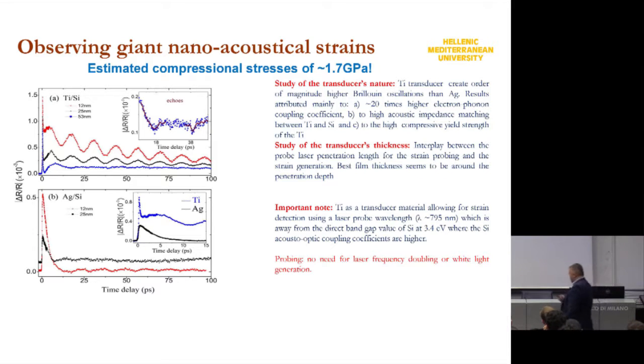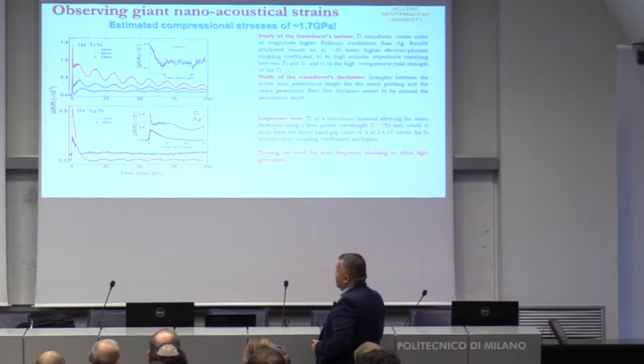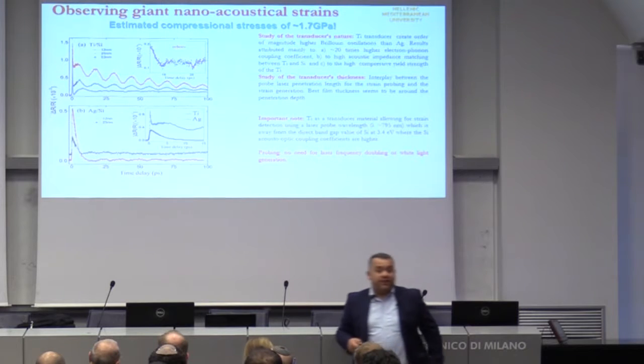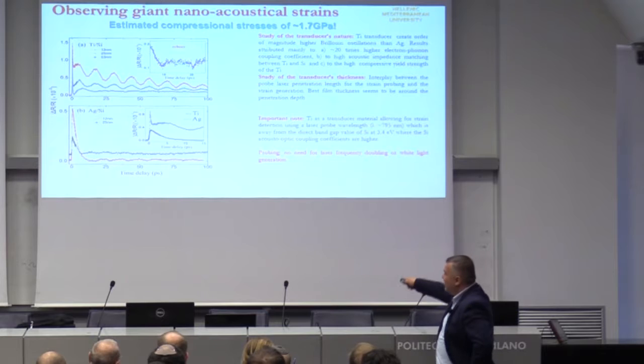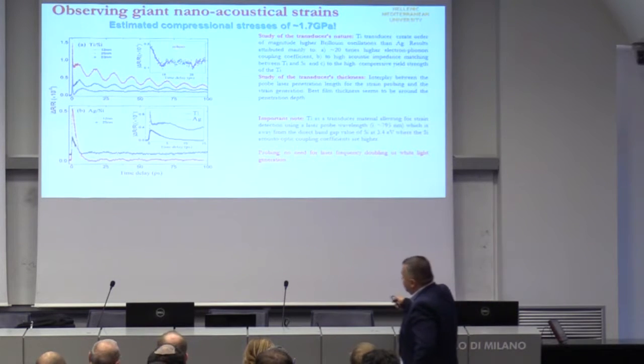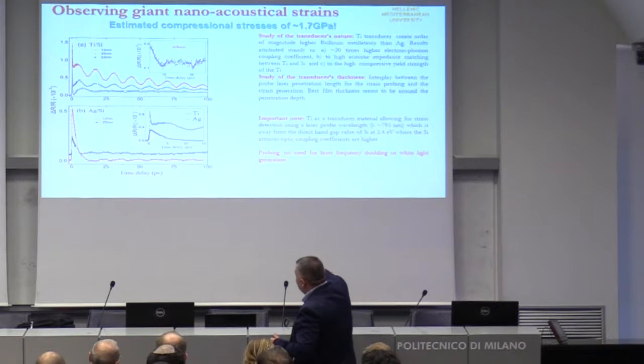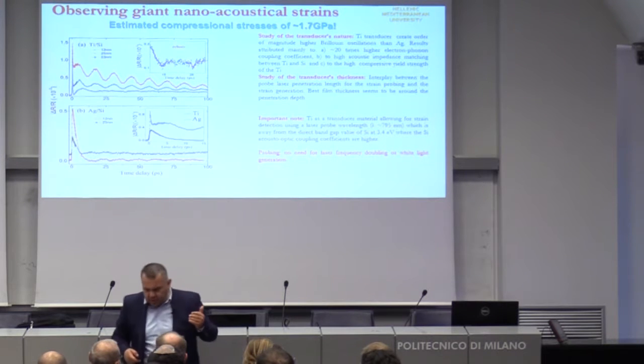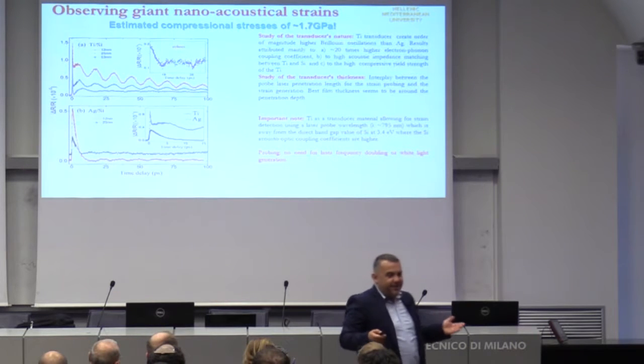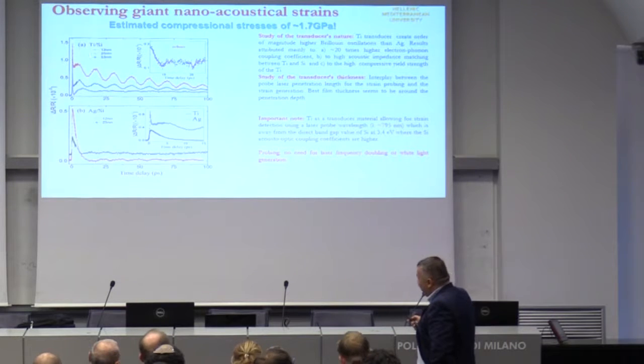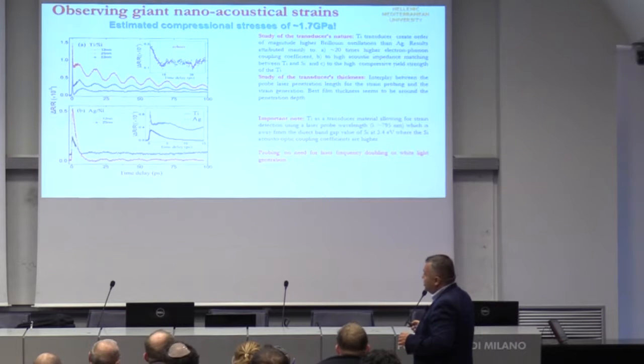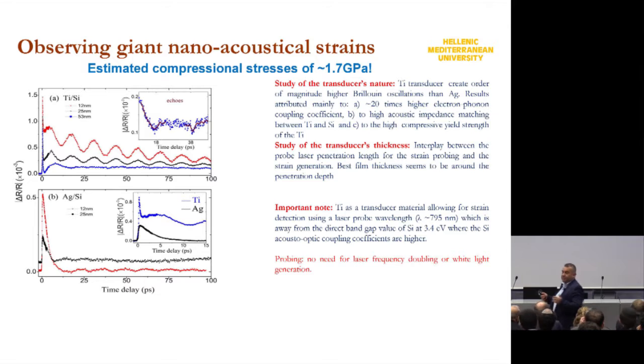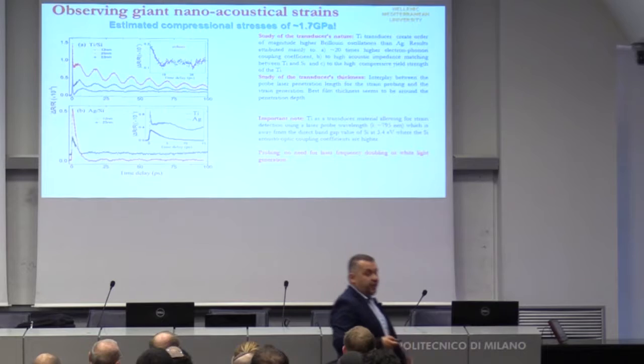Here we have silicon with titanium on it, or silver on it, another noble metal. Here is titanium and here is silver. This is the pump-probe reflectivity measurement. You see an abrupt increase of the reflectivity, which is the electron excitation. And then there is this kind of oscillating feature, which is actually the Brillouin oscillation depending on the delay. The period of these oscillations is on the order of 12, 13 picoseconds, which is related to the speed of sound inside the material, the silicon. If you do exactly the same experiment using silver, you barely observe these oscillations. So it is clear that titanium is a much better transducer than silver for this kind of application.